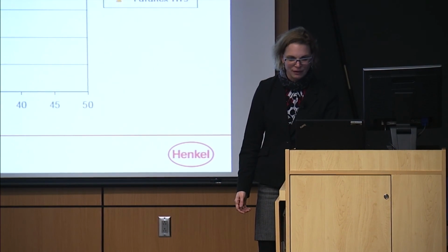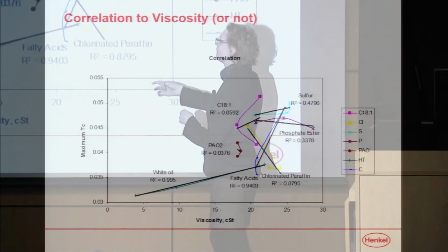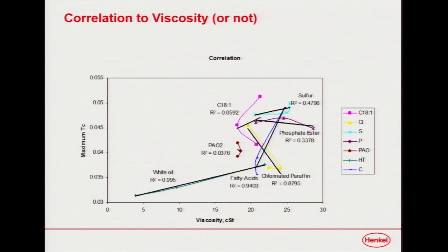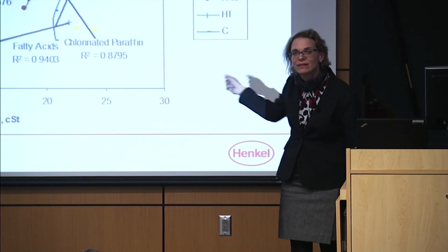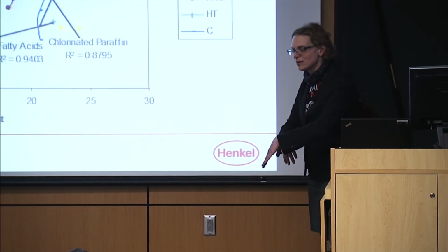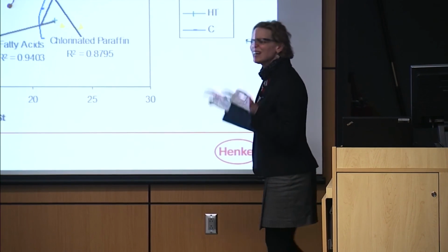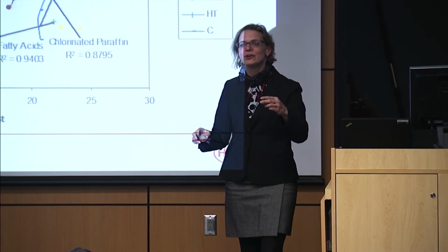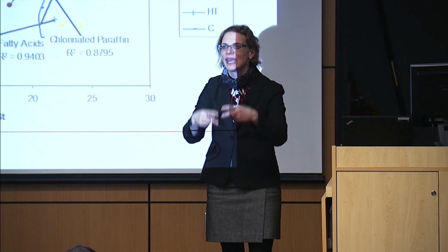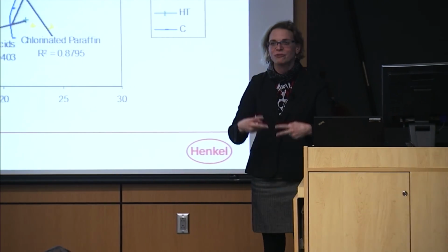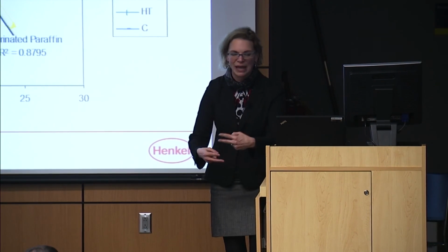It works. But when you start to get into things that are not white oil, which has an R squared of 0.995, and you start to put in things with boundary activity, well, fatty acids work pretty good, and even chlorinated paraffins worked okay, but phosphate ester? No. Oleic acid? No. Sulfur materials? Not really. So something is active chemically with these materials that causes you to deviate from normal viscous behavior. And we kind of knew that, but we couldn't really tell until we started matching chemistry to mechanical conditions. You had to have both. In this field of science, you have to have both. So if anybody ever makes fun of a mechanical engineering degree, remember, it's not a bad thing.